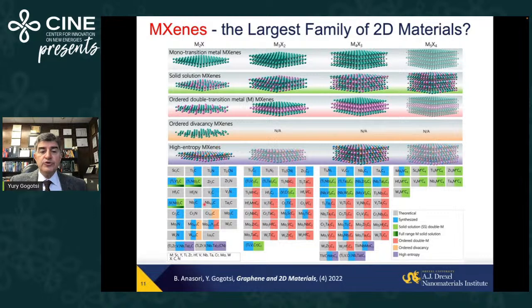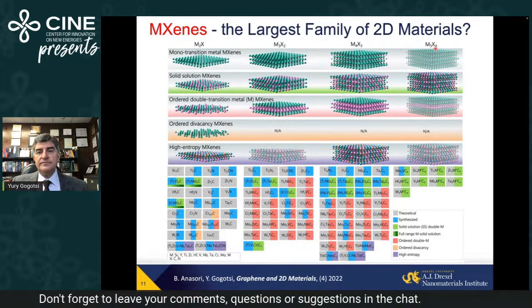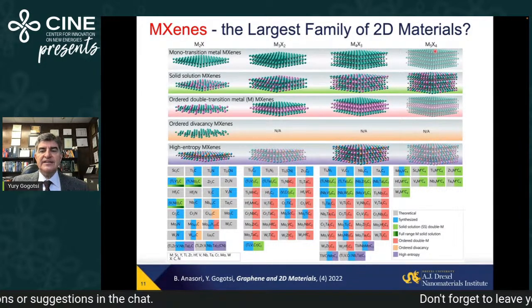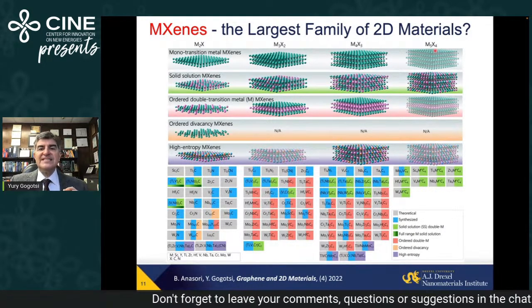But if you do the math, take a dozen transition metals, multiply by carbon or nitrogen, and 4 different structures by number of layers, you end up with about 100 simple stoichiometric compounds. Take the 10 different surface terminations I showed you. It's already 1,000 stoichiometric compositions possible.